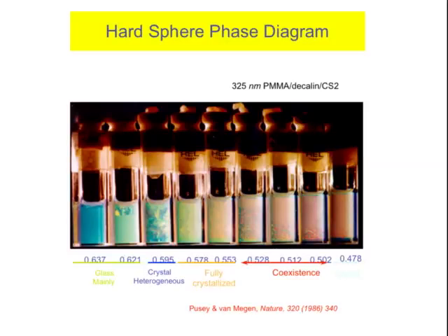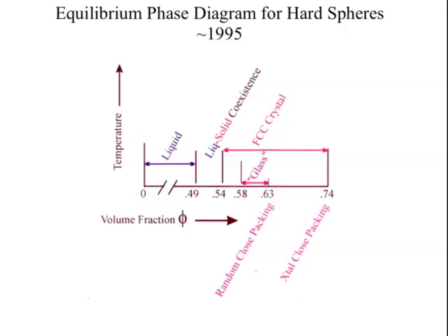So Pusey did these experiments. They're beautiful experiments. They show you that something which is just a system of hard spheres, just from excluded volume, will crystallize. And he agreed very well with the best phase diagram that they had at the time. This is the phase diagram that people had up to about 1995. Liquid up to 49%, crystal from 54% up, and maybe between 58 and 63, which is 63, 64 is random close packing, this glass phase.